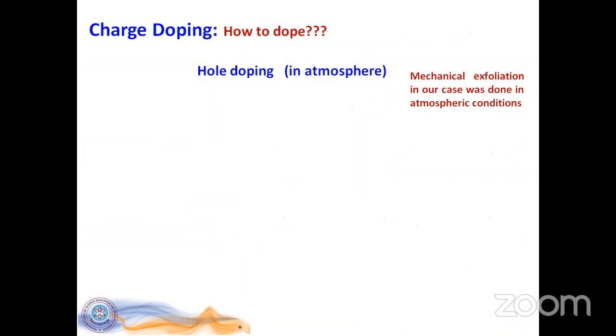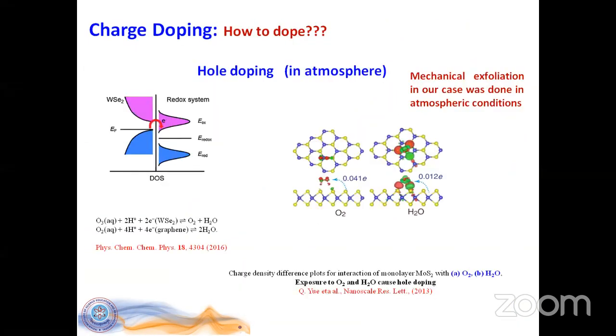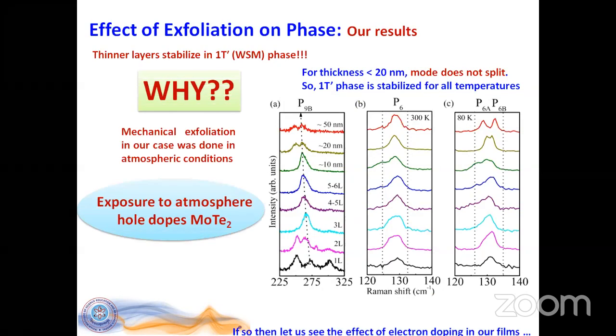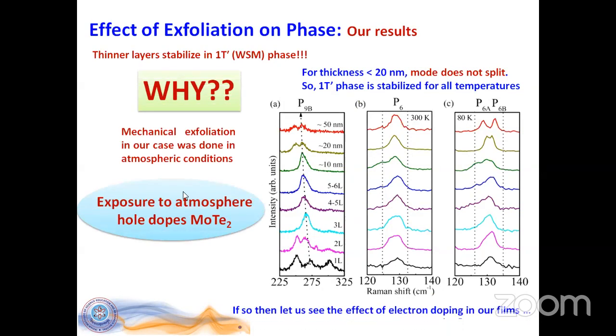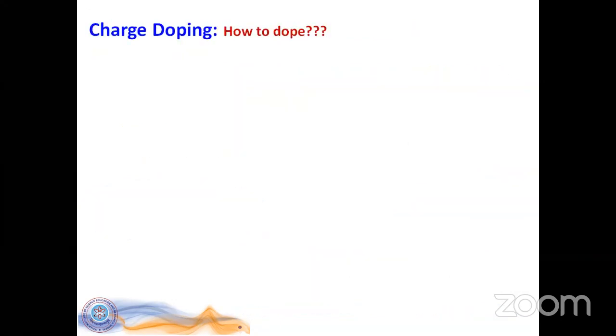But on the other hand, in our case, it is hole doping. There are many other articles on two-dimensional materials, for example graphene, sulfides, selenides. They show that if the material is exfoliated in atmosphere or exposed to atmosphere, it usually goes to hole doping, and that's where we say that it is hole doping due to atmospheric contact that is making our sample or the flakes get stuck to the 1T prime, the room temperature phase, even at the lowest temperature.